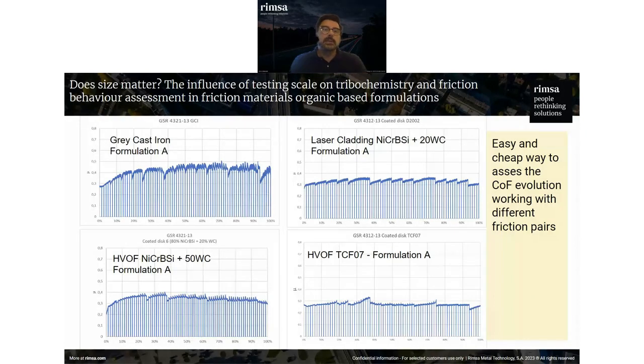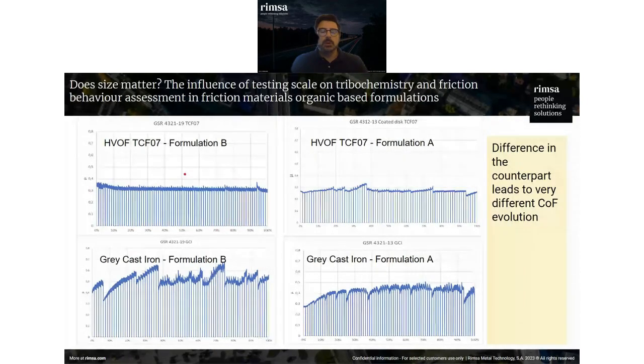for development purposes. For example, in this case, what you see here is this same profile, BDA 285, but in this case with the same formula, but using different rotors. In this case, you see how this formulation A, this is an AO formula, gives a different coefficient of friction profile when you work with a gray cast iron rotor, or when you work with a laser cladding coated rotor made of nickel chromium boron silicon and tungsten carbide, or a HVOF thermal spray nickel chromium boron silicon plus tungsten carbide, or HVOF with, in this case, TCF07. So this gives you a lot of flexibility to work with small samples, but having the confidence that the profile you obtain will be something that will be close enough to the one you are going to obtain on the